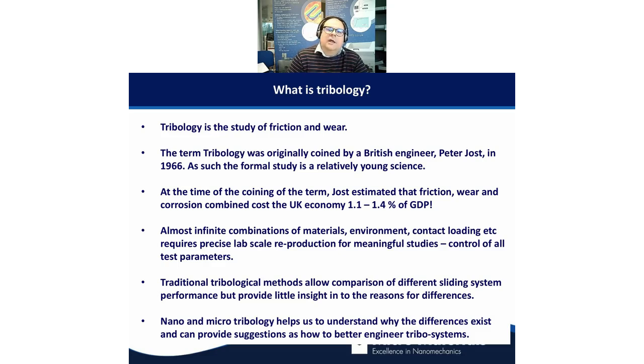So traditional tribological techniques, things like pin-on-disc tribometers, they're very good for comparing perhaps two sliding systems with one another. So you could take two samples of different surface treatments and put them on a pin-on-disc tribometer, run them until you see a significant event in terms of friction, and you can determine which of those coatings or surface modifications behaves better. But perhaps what it doesn't tell you is exactly why one behaves better than the other. And nano and micro tribology helps us to do more highly specified tests to try to understand why one sliding system perhaps performs better than another, and gives the engineer something that he or she can feed back into a development process.